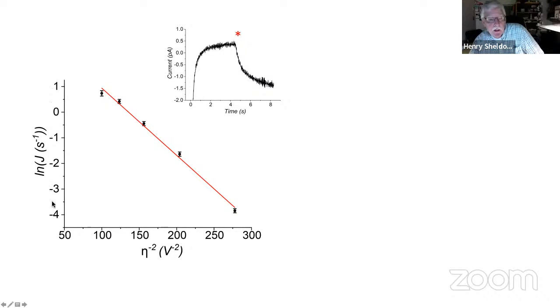That's what's being plotted here. And then we're plotting this as 1 over the overpotential squared, and that comes from classical nucleation theory. I'm not going to show the equation, but the theory says if you plot log of the rate of nucleation versus this inverse of the square of the overpotential, you should get a straight line. And indeed, we do. It's a straight line, and the error bars are small because we measure lots of events up here.